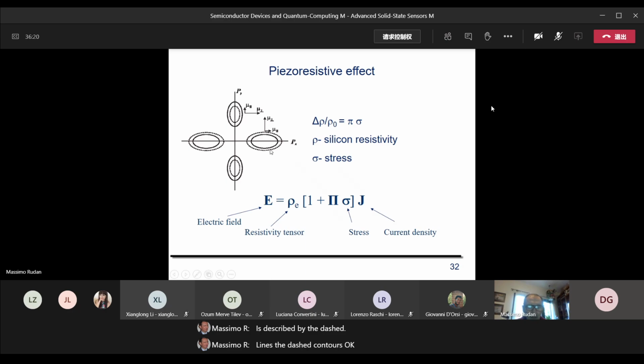You see here the dashed contours along the x direction are larger. Instead, those along the y direction are smaller. And they are not visible in the figure, but also those in the z direction will become larger, okay? In conclusion, by applying a stress, we have a population of the minima such that the conduction is dominated by the transverse mass, a population that is larger. So we have more electrons that are light, fewer and fewer electrons that are heavy, okay? So by this simple trick, we increase the mobility of the material, okay?